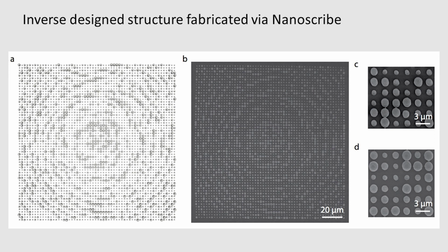And this is how the zoom-in looks. The way this Nanoscribe fabricates it, they essentially create a pancake-like structure, but each pancake has a varying diameter, and that's how you make a sphere. Of course, you cannot make a full sphere because a sphere doesn't have any contact area, so it's going to fly off. So you have to make almost an 80% sphere, and then we just have a base.